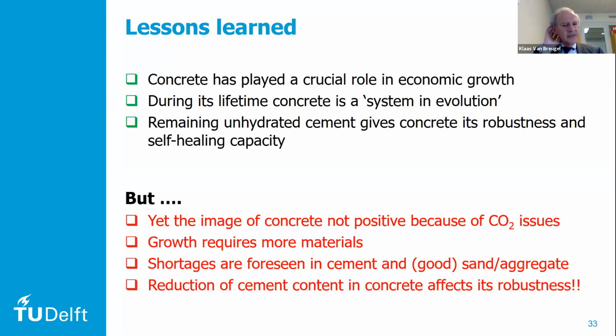And for that reason, and that's a trend today, we try to not use that much cement anymore in our concrete. First of all because of the CO2 issue, secondly because it is expensive, and thirdly because there is maybe not enough. So we reduce the amount of cement in our concretes, but that means that we also take away some of the robustness of the concrete. If we do that, then we might be smart to introduce artificial healing